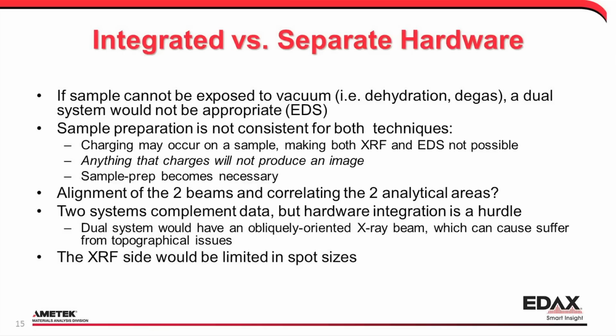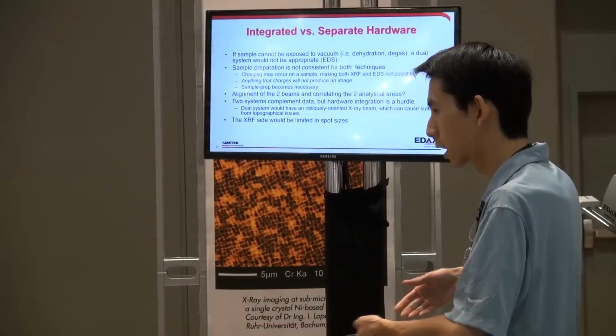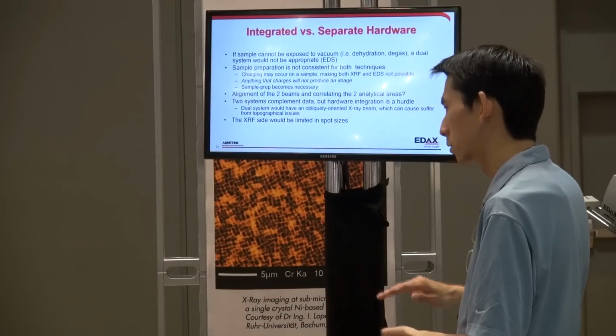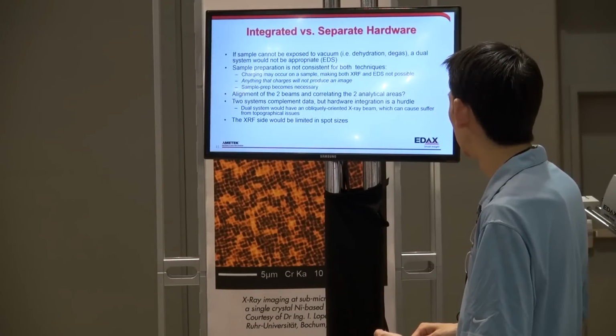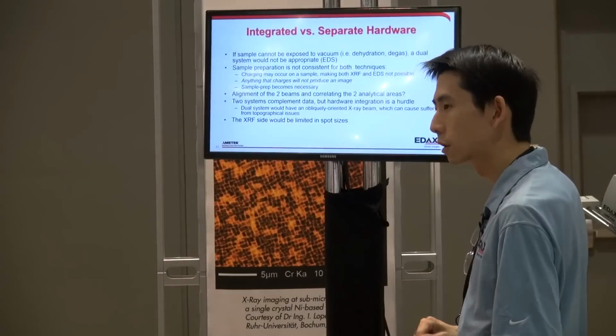Also, there's alignment of both of the beams, the electron beam and the X-ray beam, and getting them to correlate on the exact same areas is generally easier said than done. And between those two beams, the XRF beam will have to be an oblique beam coming in at an angle, and that can bring up some topographical issues.